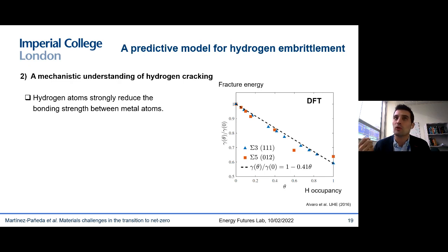The first one is that if you do atomistic simulations, like DFT or molecular dynamics, of grain boundary decohesion, or basically fracture energy or surface energy degradation with hydrogen occupancy, you see that if your grain boundary is full of hydrogen, with an occupancy of 1, there is a very significant reduction in the fracture energies, a 40% reduction. So that's quite interesting. If my grain boundaries are full of hydrogen, they're going to be quite weak. So that could explain things. Of course, first of all, we need to answer the question of where we are on this x-axis, right? Are my grain boundaries going to be full of hydrogen, or are they going to be rather empty? Because if they're rather empty, there must be something else happening in there.